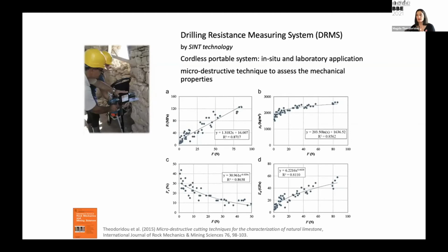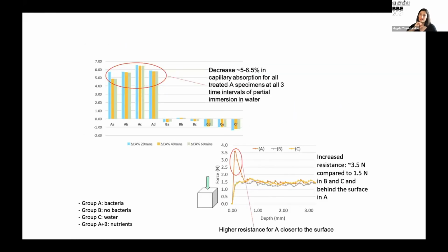portable drilling resistance measurement system. There is previous research that shows strong correlation coefficients when comparing these values with various standardized but destructive laboratory tests. And another benefit is that, instead of getting just bulk properties, this test records the in-depth profile of the material's resistance to drilling. So we can detect denser microstructures, voids, or consolidated areas.